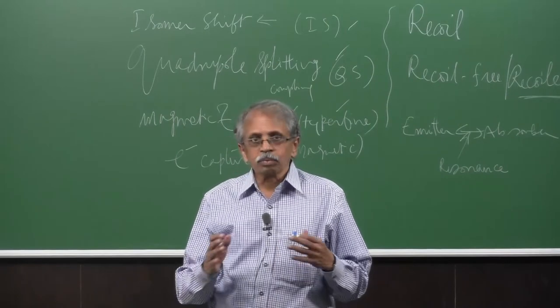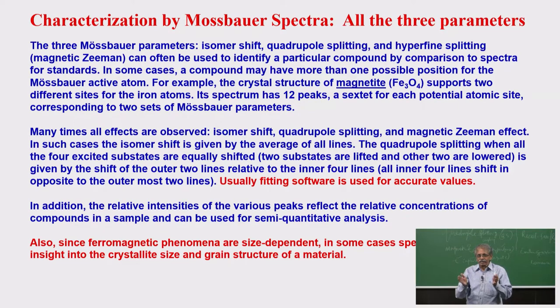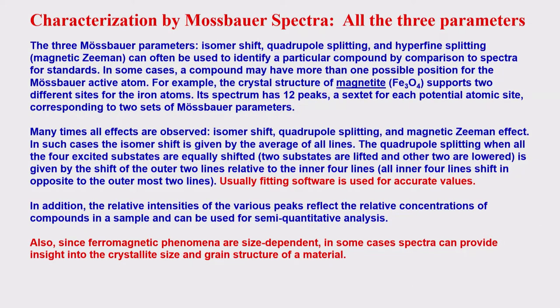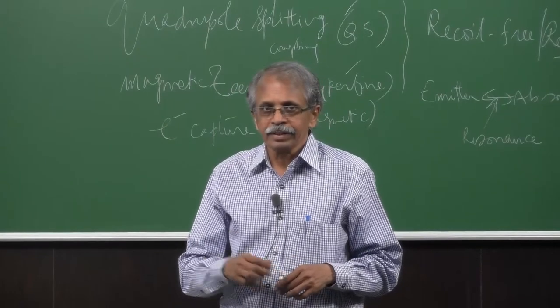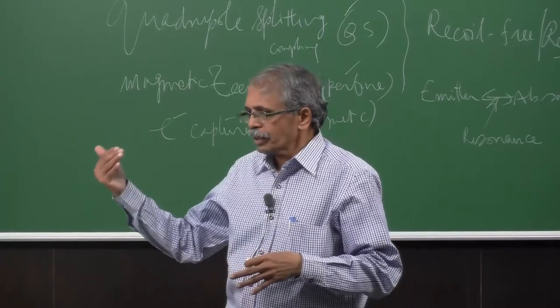The isomer shift will help because their isomer shift values will change, and quadrupolar couplings depend upon the symmetry for each center. The kind of electric field — symmetric or asymmetric — will also shift or split your lines. The lesser the asymmetry, the lesser the quadrupolar coupling; the greater the asymmetry, the greater the quadrupolar coupling. You can also apply an external magnetic field, or some magnetic materials will internally produce the magnetic Zeeman effect.